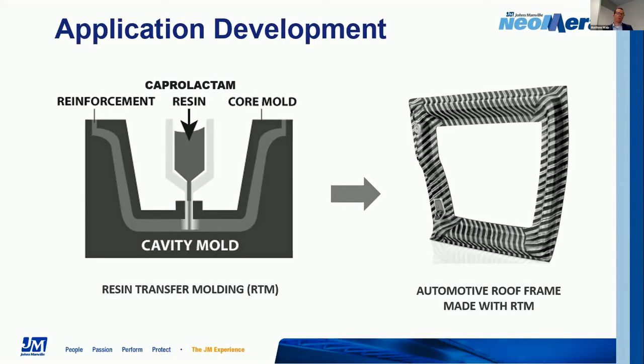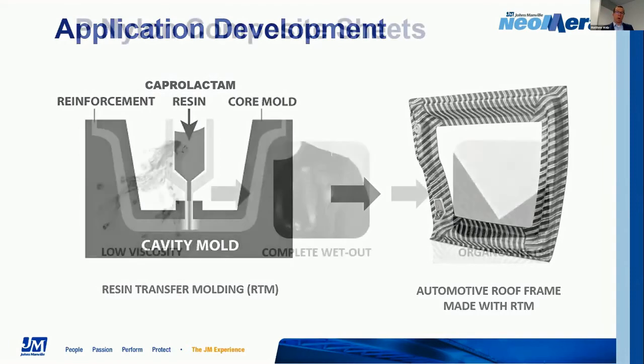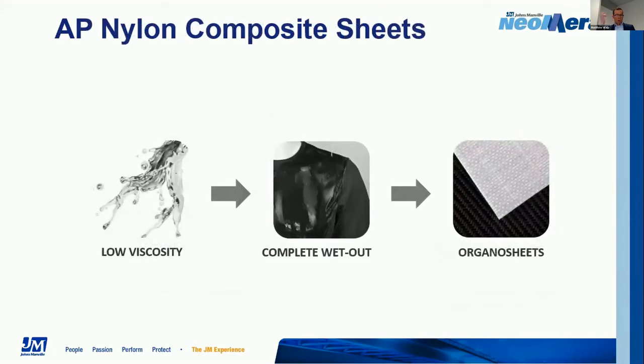And so as JM looked to how this technology would grow and how we could potentially do more with it, we started looking beyond just selling it in the RTM space and maybe doing it on our own. And this is where we introduce our composite technology, our thermoplastic Organosheet technology. So, if you're familiar with the RTM process and how AP nylon is produced in that process, first of all, we're running at rather lower temperatures from a thermoplastic standpoint. So right around 90 to 100 degrees C is what we're handling the resin system.